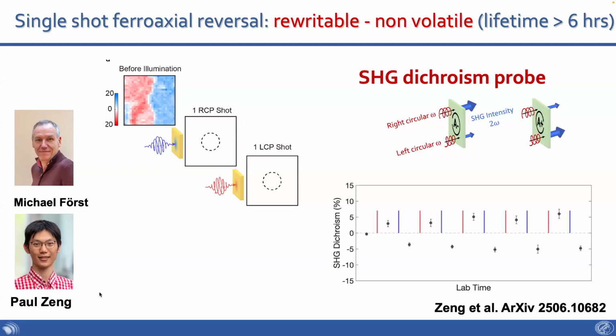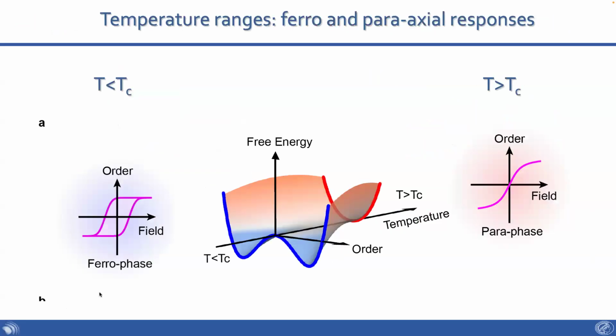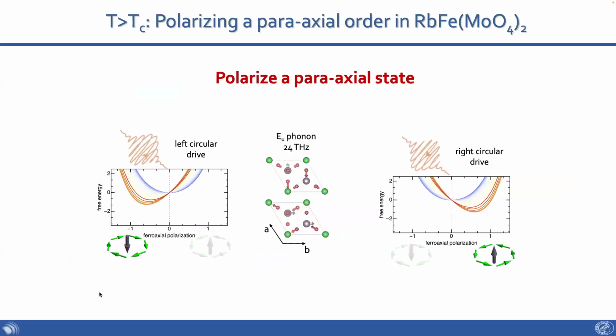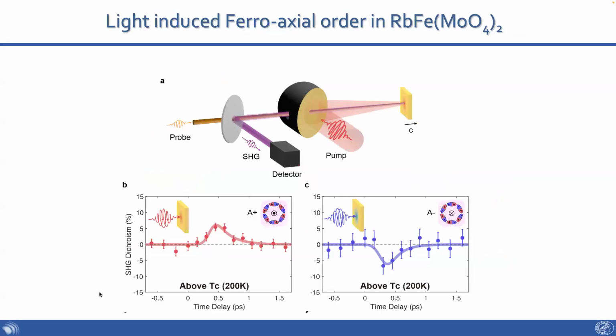So anyways, the other thing that I want to tell you here is another thing that Paul explained to me. He said, well, when you go above TC, you're going to have some form of paraxial system. The system really doesn't have two stable states, but I should be able to use the light field to polarize my non-ordered state into an axial state. And these are the equations of motion. Instead of having the double well, I have something that on average doesn't really break a symmetry. But if you drive it, you're going to switch to the right or switch to the left. Your energy, because of the Q cross Q dot times A term, is basically pushing this down. And you can see now that if you redo the same experiment, you can generate an axial state above TC. So this is a light-induced axial state that only lives for a very short time.